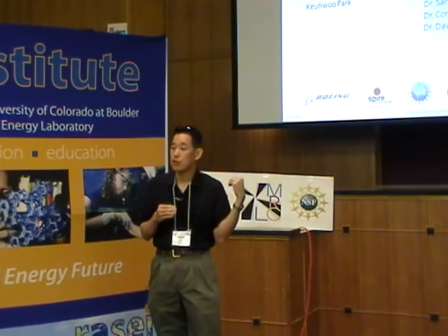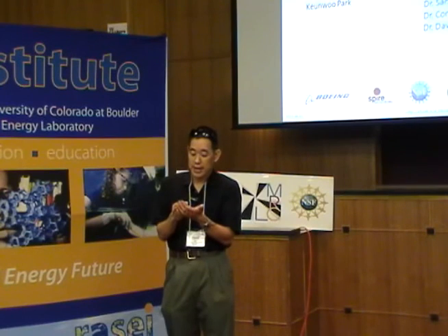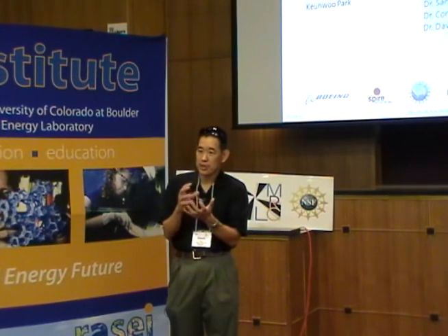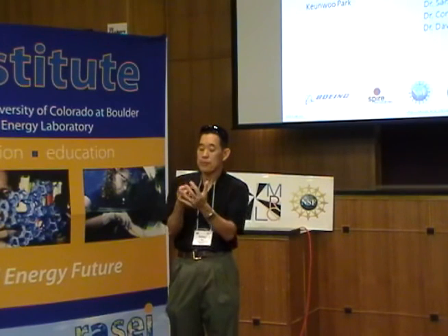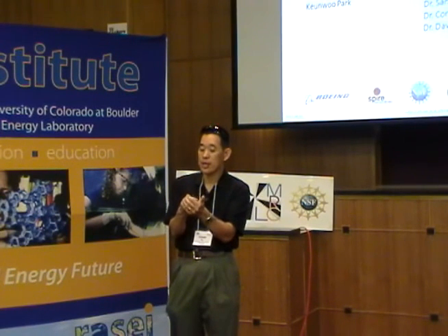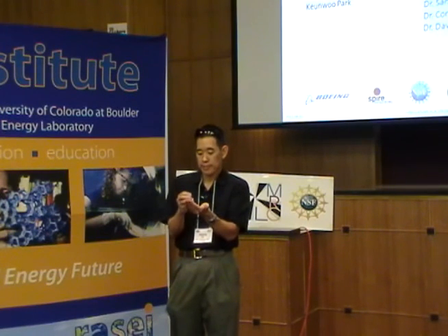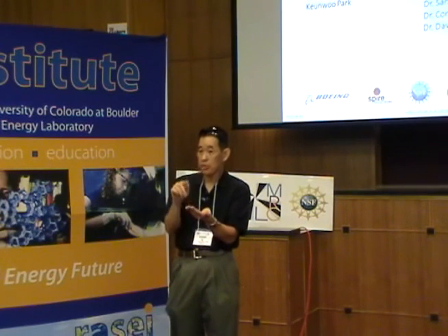And we incorporated those because it gives you a little more flexibility in terms of the critical thicknesses and so forth for a given extension of the range of wavelengths that are absorbed. But because the dots are ideally pure indium arsenide, or certainly indium rich, the potential wells are very deep.